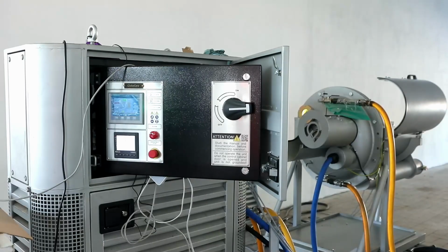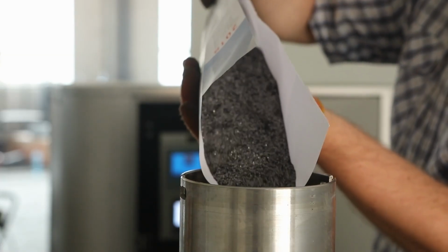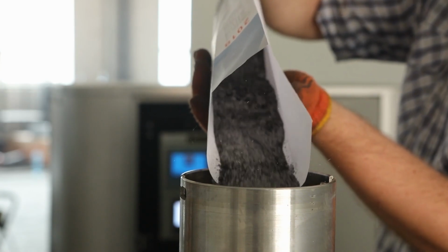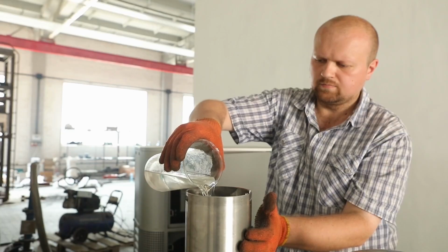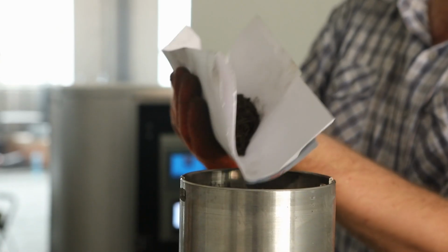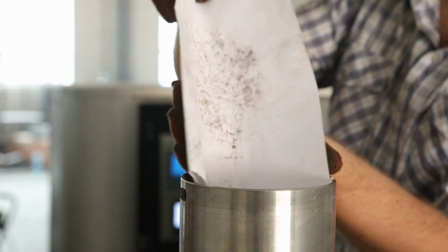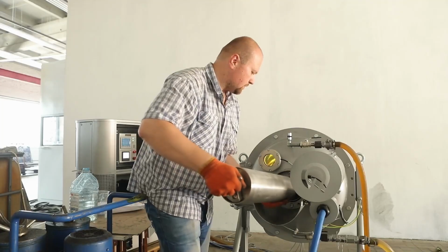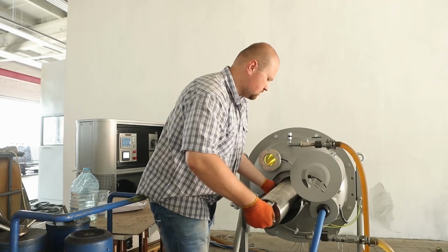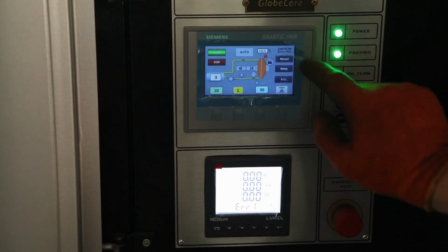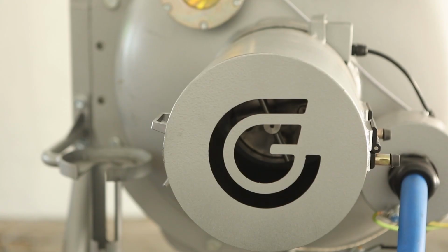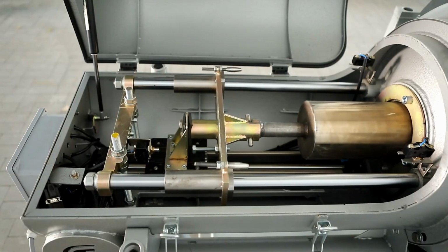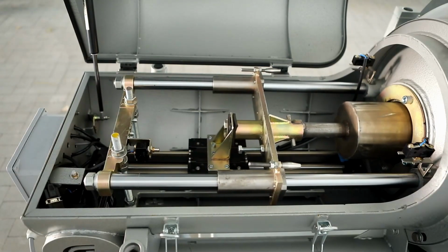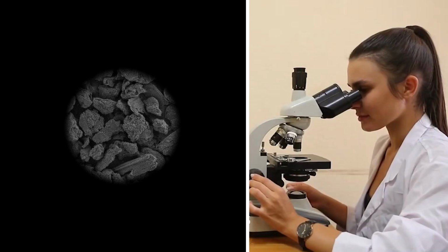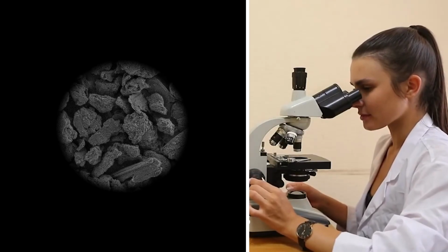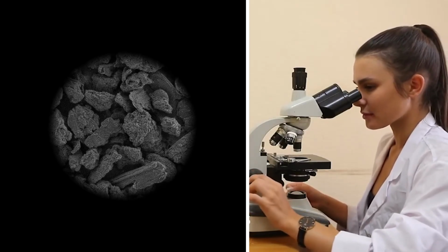First, we prepared 600 grams of graphite, 1.65 liters of distilled water and 500 grams of steel ferromagnetic particles with a length of 15 and a diameter of 1.5 millimeters. All of this was placed in the working chamber of the vortex layer device AVSP-150 and was milled for 10 and 20 minutes. The samples were then examined using a TESCAN VEGA 3 scanning electron microscope with a measurement limit of 3 nanometers. You can see the image obtained with the microscope on the screen now.